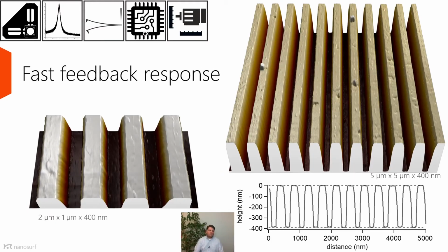As I said, the controller was designed to have a low feedback latency, and also the scanner is stiff, so it has a high resonance frequency. That means it can respond fast. It can respond faster than comparable scanners out there on the market, as it's a direct drive and stiff architecture. And this is important, for example, looking at such grating samples. They are often used in industry for different purposes. You have such gratings, and they're quite demanding. So you have very deep trenches with steep walls, and if your feedback is too slow and cannot follow these structures nicely because your piezo is too slow or your feedback itself is too slow, you would just ruin your tip. Over the course of a few lines, you may see that your tip just degrades, and you cannot follow those nice trenches anymore.